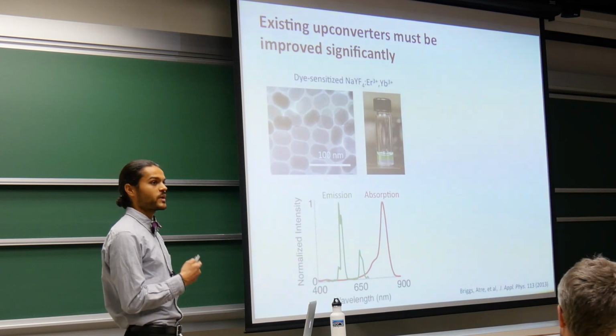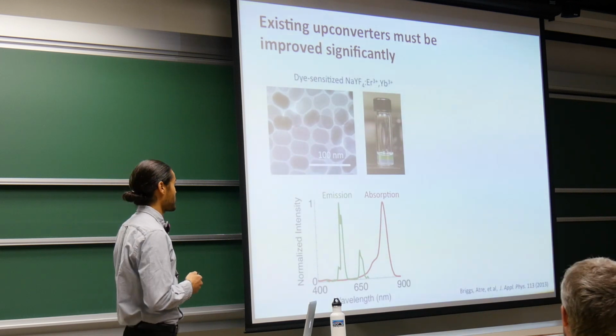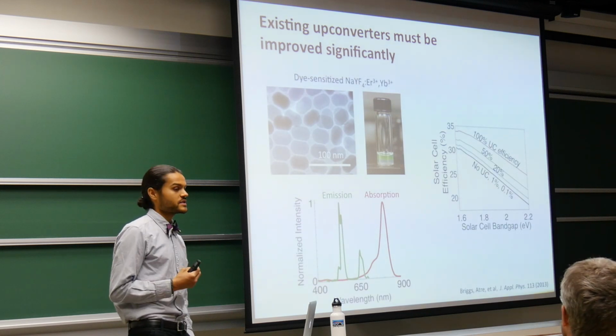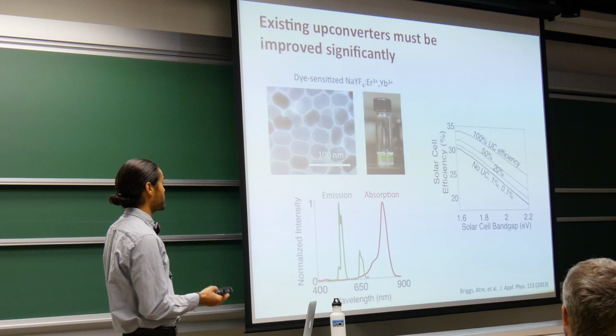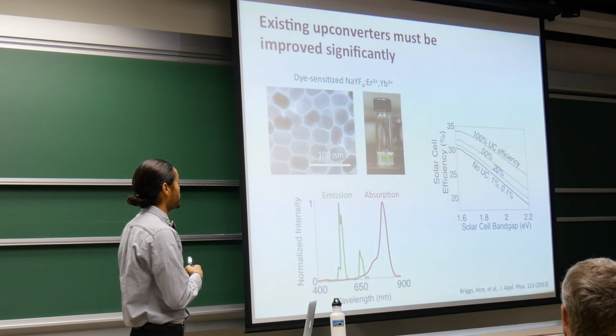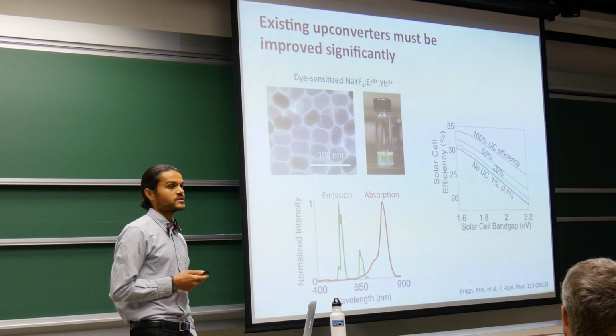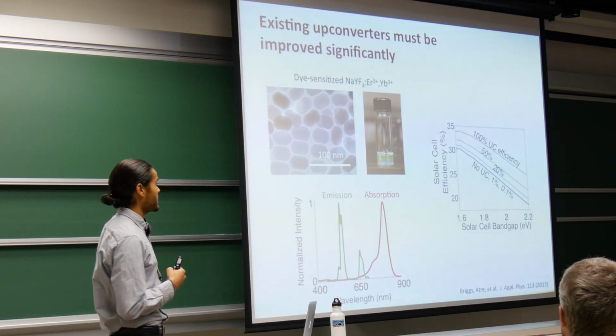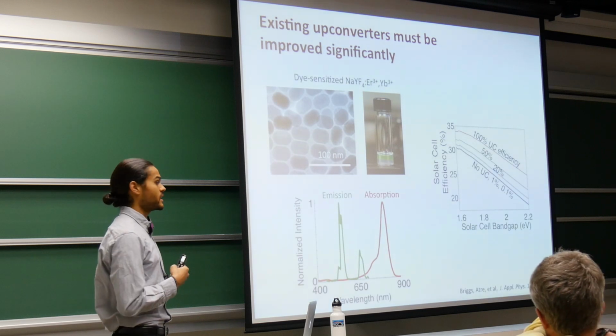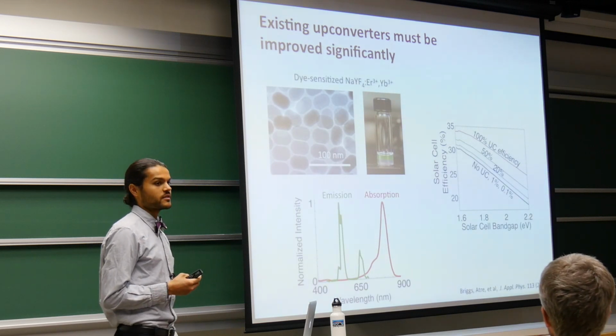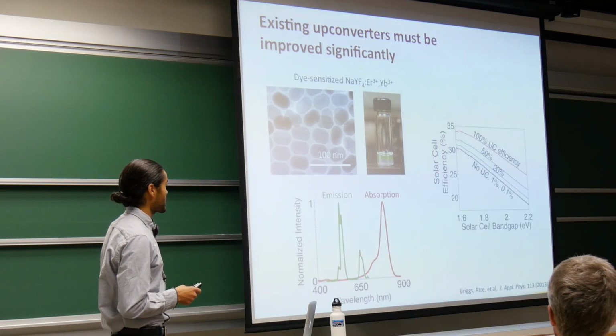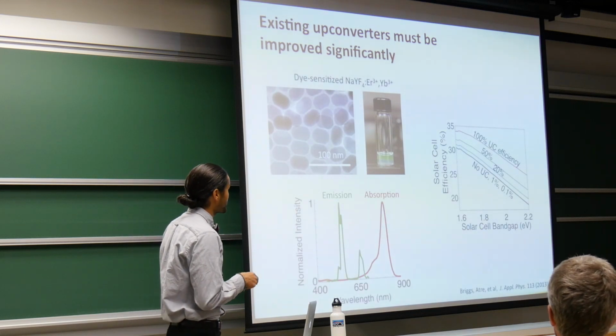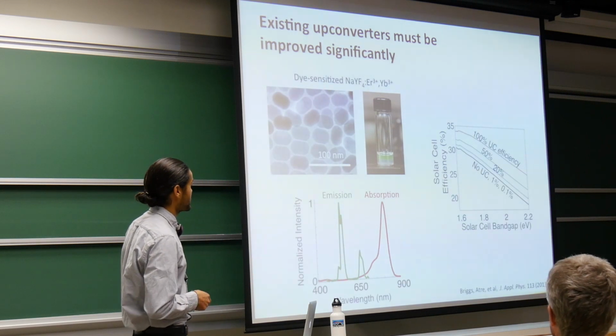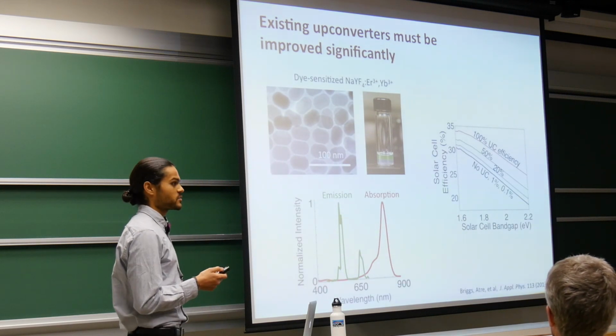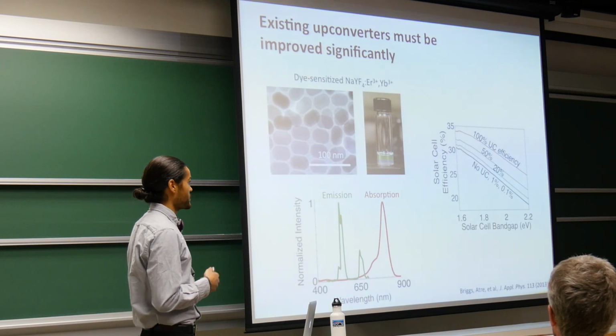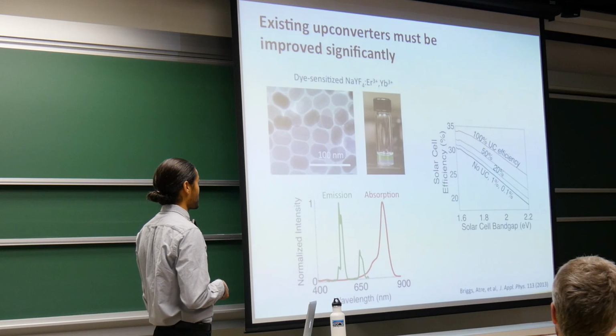Now, if we plug these exact spectral characteristics into the model that I just described and assume various upconversion efficiencies, we can see that with a 100% efficient upconverter operating in this spectral window, we can calculate an improvement in solar cell efficiency of as many as 6%, depending on the solar cell bandgap. Unfortunately, in reality, these particles are only about 1% efficient in terms of their ability to upconvert light. So as you can see, the lowest line, that dark or black line on this plot, corresponds to the no upconversion case as well as this 1% upconversion case. So essentially, there's no enhancement for efficiencies that are as low as they are today.